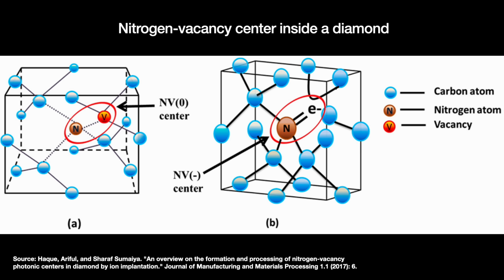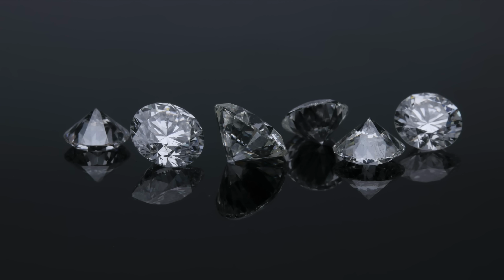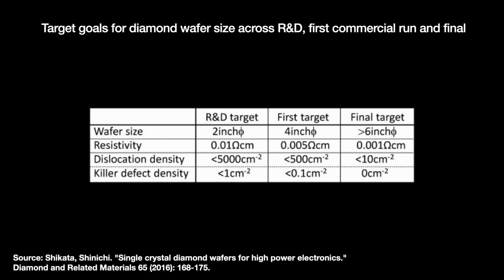I recall from my visit to the MPCVD lab them saying that a 2-carat gem quality diamond might take about 2 weeks to produce. The target width to go commercial is about 4 inches, with a killer defect rate of 1 per 10 square centimeters. But single crystal wafers, right now, just 10 millimeters wide, can cost up to 10,000 times of equivalent sized silicon. We are far from ready.